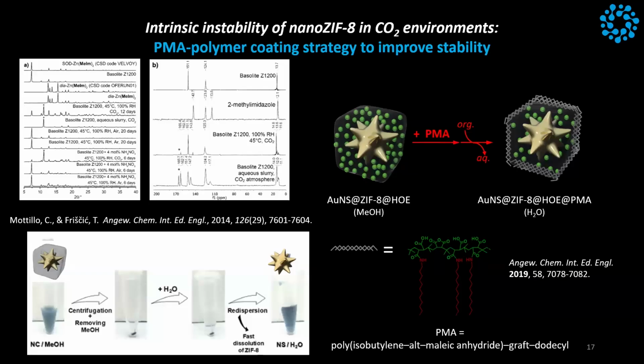Okay, so already 12 years ago, it is known that ZIF-8 is not stable in water. And the reason it's not stable in water is because of the CO2. If you have CO2 in the water, CO2 chelates zinc and destroys it. I didn't know that at that time, but when you put a polymer or something that prevents CO2 absorption or takes CO2, you prevent that you destroy the MOF. So any zinc-based MOF with CO2, we have to be careful, and that's the reason we use this PMA coating that allows us to do a lot of work in that direction.